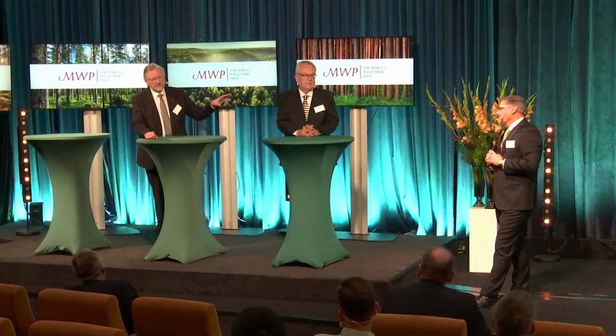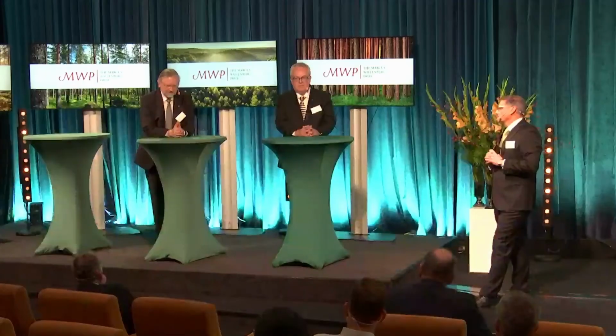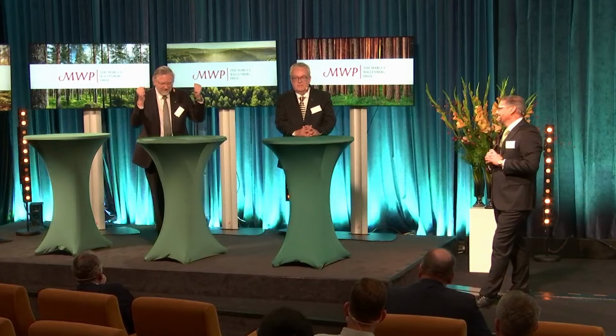So there is already progress. When we look at viscose, we have, let's say, in the best case, 9% cellulose in the solution. Now we talk about 13 to 17%, but it's actually not very good. So we need to go to 40, 50%. And the other thing is, you were talking about we urgently need something which replaces elastane. I fully agree. But what is it?